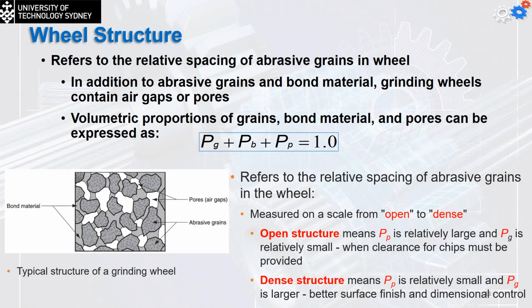from open to dense. The open structure means that the value of the porosity is going to be large, and the PG, which is the grain value, is going to be relatively small when the clearance of the chips must be provided. Dense structure means that the Pp, the pores, is going to be relatively small, and the PG is going to be larger, and we're going to have better surface finishing and dimensional control for the workpiece.